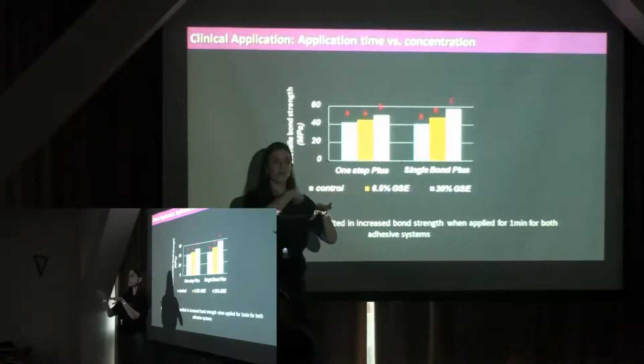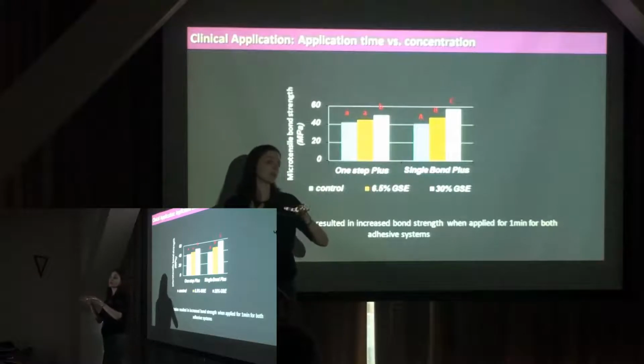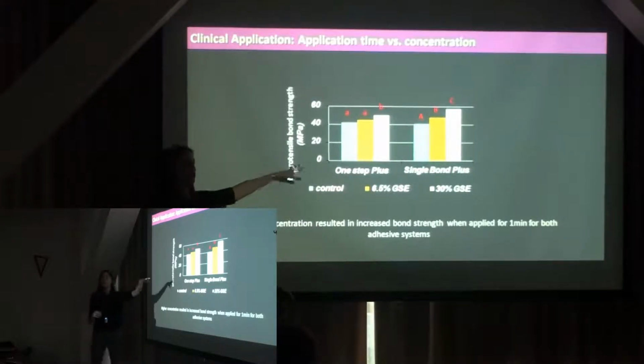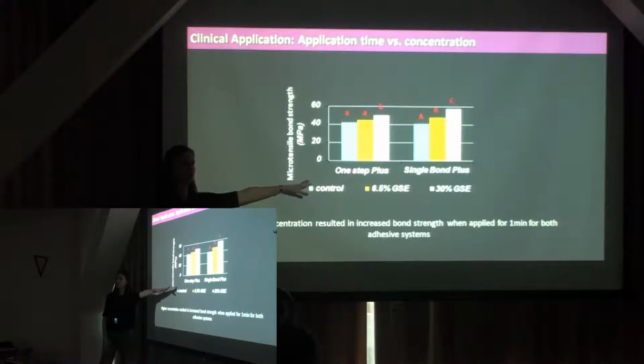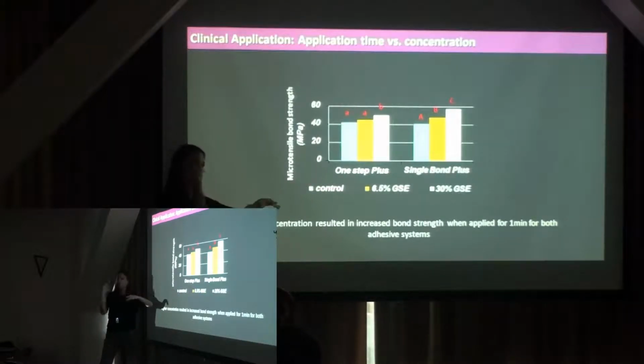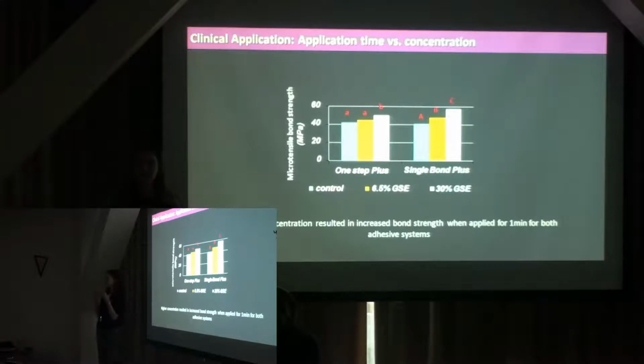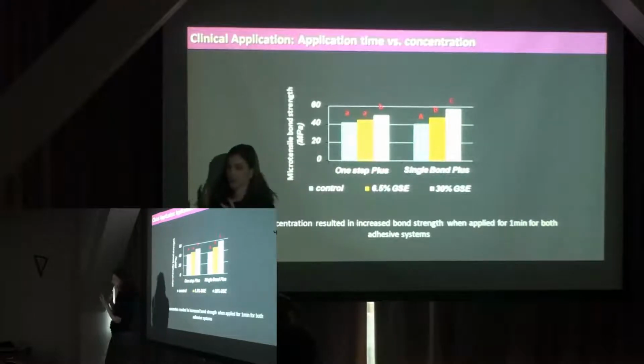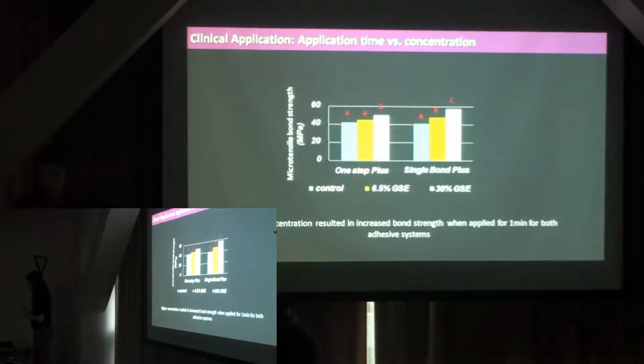So you etch, you rinse off the etchant, then the surface has to always be moist, and you introduce the solution with the 6.5 or 30% grapeseed. Then you rinse that off, then you introduce your bonding system over this moist surface. We need some moisture over the surface, otherwise we can't create that hybrid layer because the collagen won't collapse. All right. So this increase in bond strength was more predominant with the higher concentration.